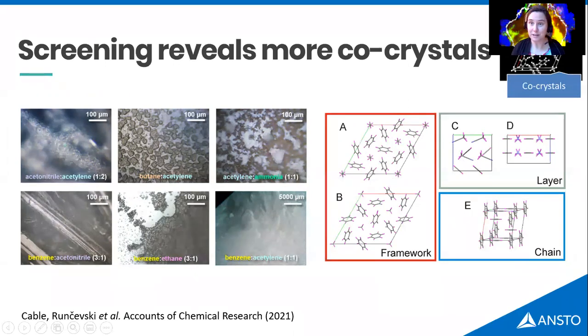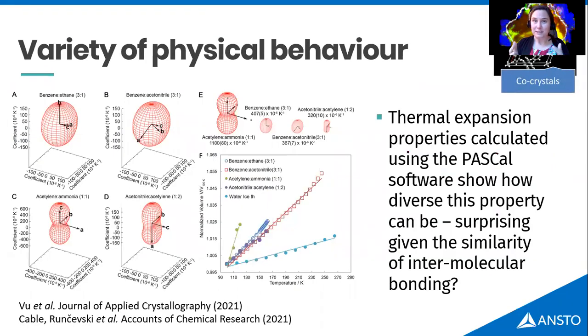We've recently written a really nice review paper about this work and where we think it's all going, so I really urge you to go and look that up in Accounts of Chemical Research as well. One of the things it's revealed is that despite the fact these are all quite simple molecules, and you'd have thought that their intermolecular bonding, though weak, would be quite similar, it already shows quite a variety of physical behavior. Nowhere more so than with just good old thermal expansion, where you can see the acetylene ammonia, one of those layered materials, has a massive thermal expansion when compared to the other materials. And one thing that's quite surprising is how big it is compared to acetonitrile acetylene, which is a reasonably similar layered material in some ways.